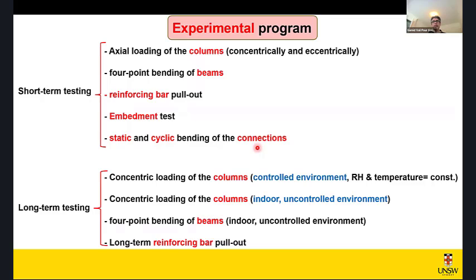Also, we'll look at the long-term performance of the columns, meaning that we applied loads on the columns and we monitored them for over a year, and some beams which are at least at the moment under the loads, and we are planning to monitor them for 18 months to 24 months. And I show you again some primary results of those long-term bending tests. And also we have long-term reinforcing bar pull-out, right?